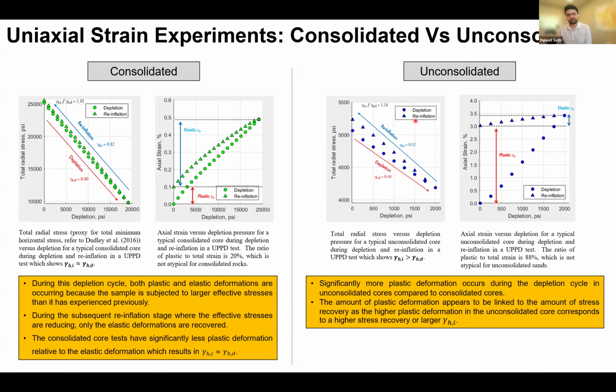That is not the case, however, in soft unconsolidated rocks, where, as you can see, if you look at the slope of these lines, it's very different for depletion and reinflation. And if you take a ratio of these slopes, 0.5 to 0.4, the injection to depletion coefficient is actually much larger than one. It's 1.18 in this case. Also very interesting on the strain side, if you look at strain versus depletion, most of the strain in the case of soft unconsolidated samples is actually plastic, meaning it's not recovered during injection, right?